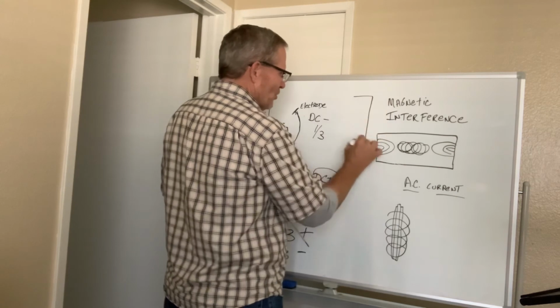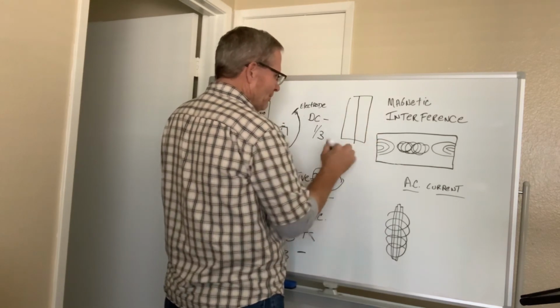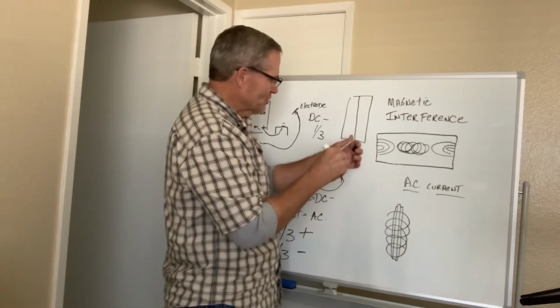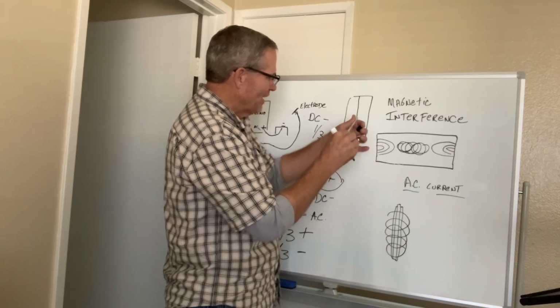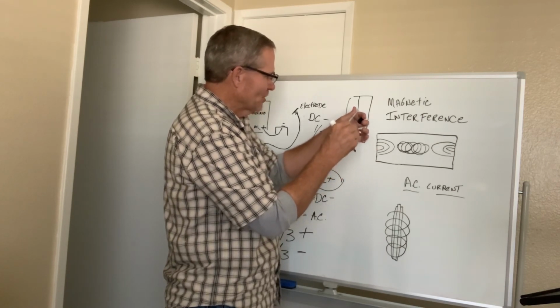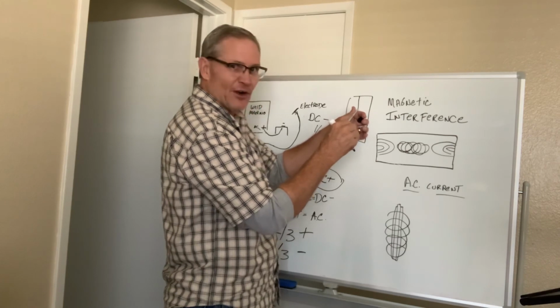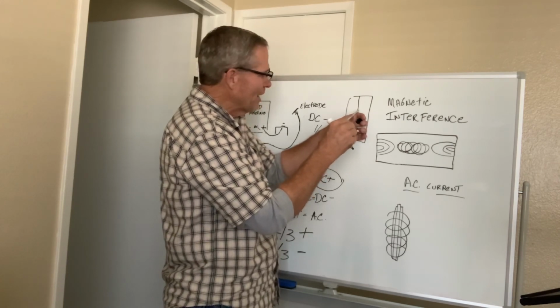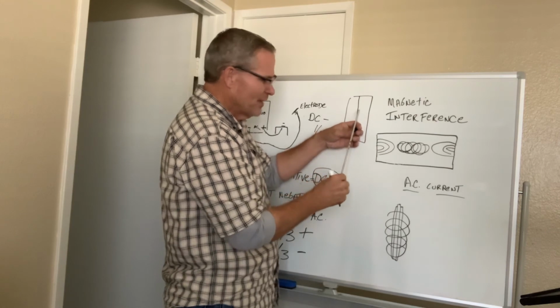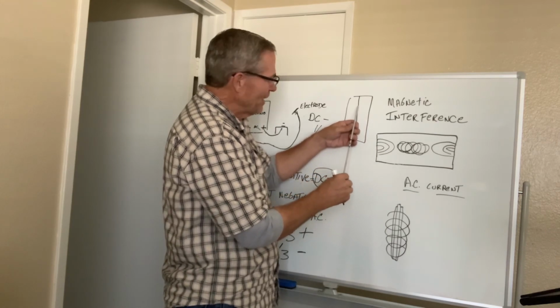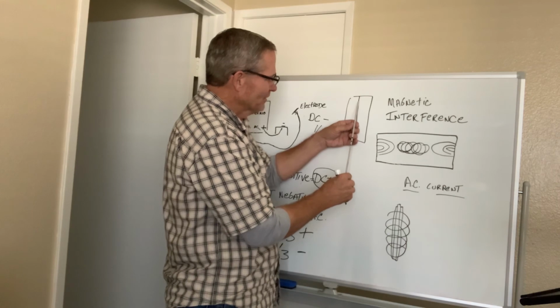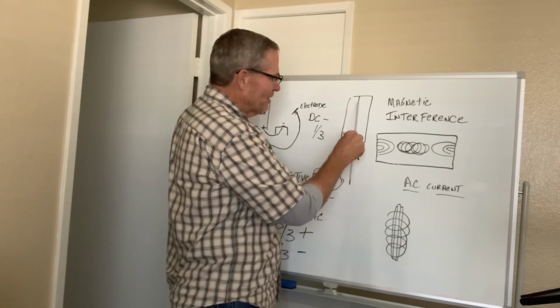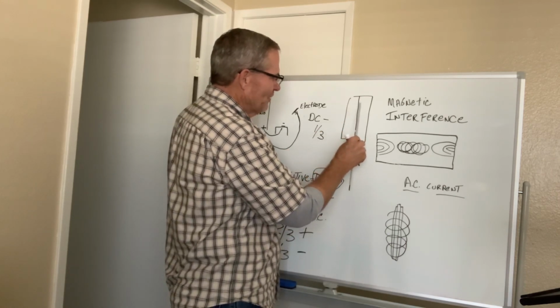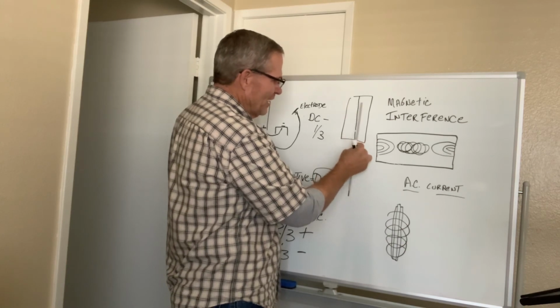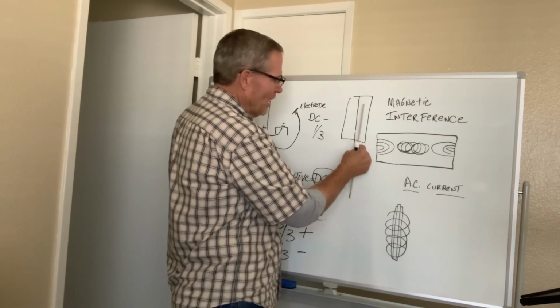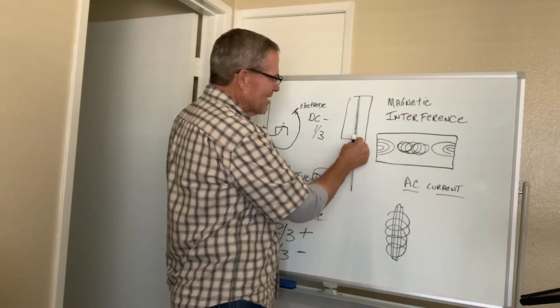If I'm welding in the vertical position, if I'm welding a plate here, I would start out welding just fine, and then about right here, I start getting a lot of that magnetic interference known as arc blow. And what I would end up doing is having to lower the electrode down in order to maintain control of this. I've had so much arc blow in the past that literally the electrode is almost vertical. I'm almost in this position as I'm finishing the weld.